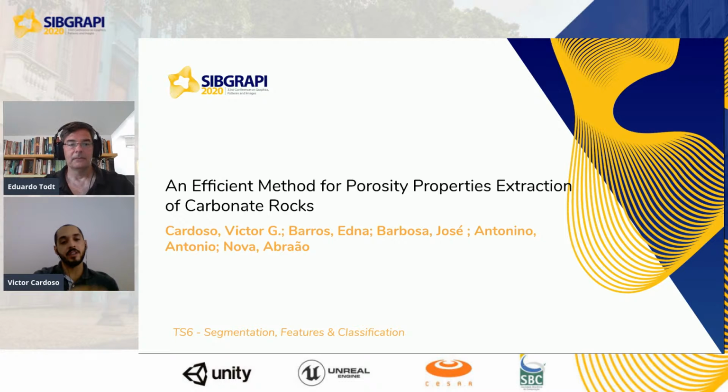After the selection of the region of interest, which is done autonomously, the next step is the filtering step, and this filtering operation was done by a Gaussian filter. After that, we proposed a segmentation technique based on global threshold segmentation that calculates the threshold value automatically based only on the histogram data. So at every imported image, the algorithm tries to find the threshold limit based on the histogram of each image, according to the information that we had about this kind of data. In this case, it is related to carbonate rocks.